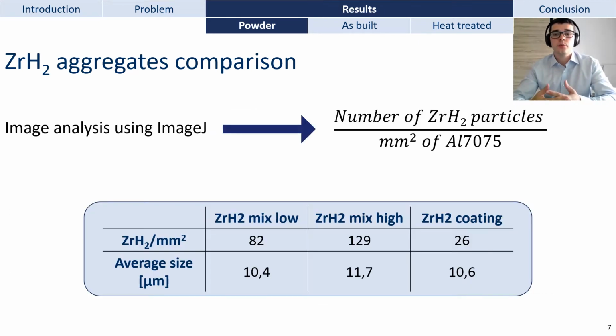So we are able to quantify the amount of zirconium hydride particles by using the image analysis software ImageJ. We were able to count the number of zirconium hydride particles and divide it by the surface occupied by the aluminum 7075, and thanks to that, obtain the density of zirconium hydride aggregates for the three different alloys containing zirconium, based on a series of SEM images like the one you have just seen.